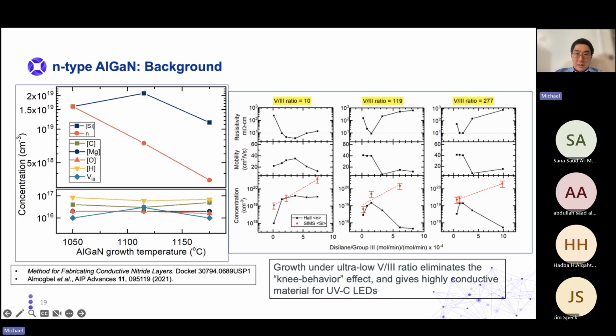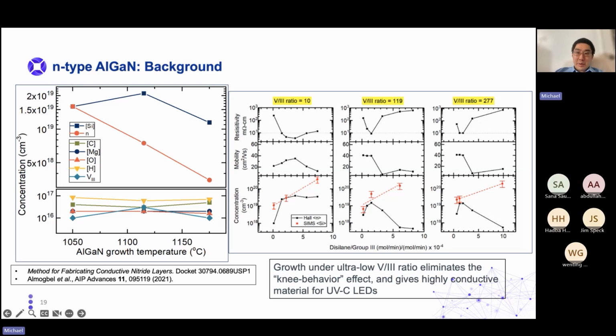We discovered early on, Dr. Abdullah Al-Meghbul discovered, that if we decrease the V/III ratio, we can get rid of a knee effect that we observe in our material. So this knee effect is basically what happens when you try to dope AlGaN, especially high aluminum AlGaN, around 65% aluminum, typically used for UVLEDs because of its transparency to UV light. What happens is, as you flow more and more silicon, the resistance of the material drops off, as you would expect, but then quickly shoots back up due to compensating behavior.